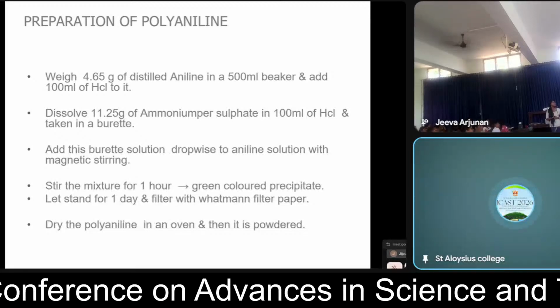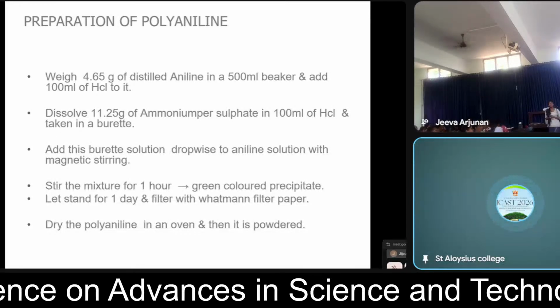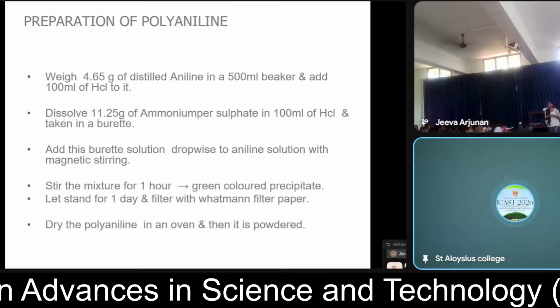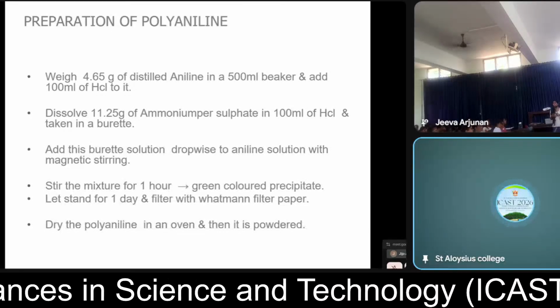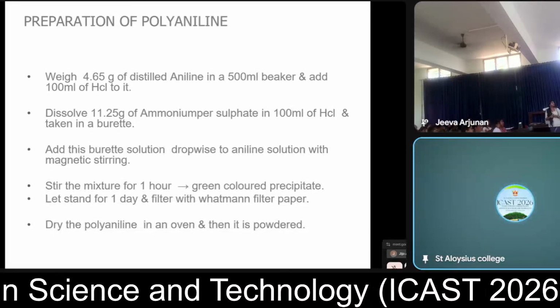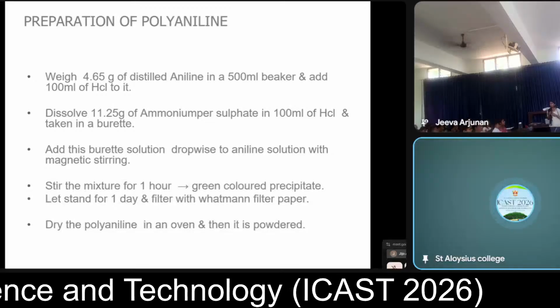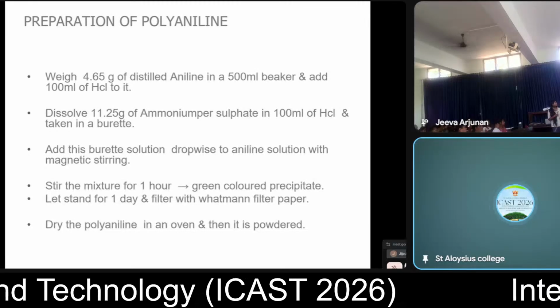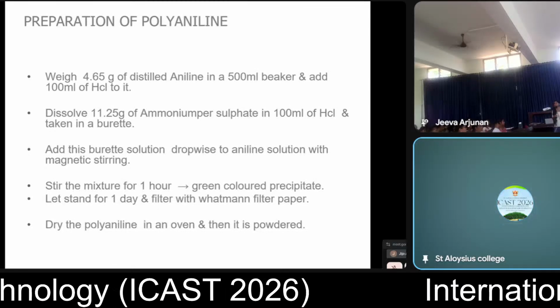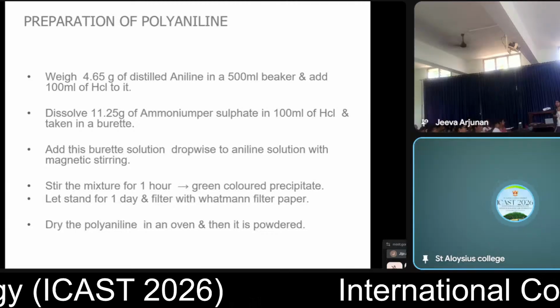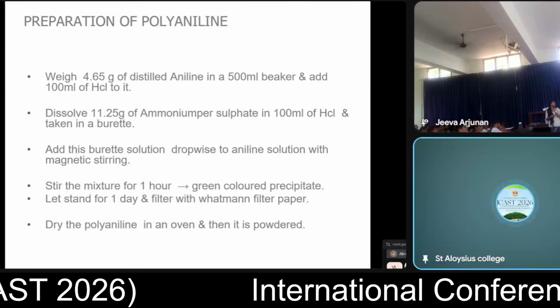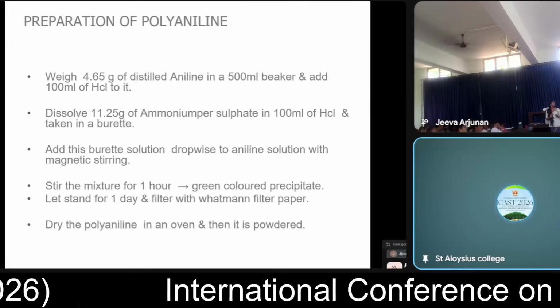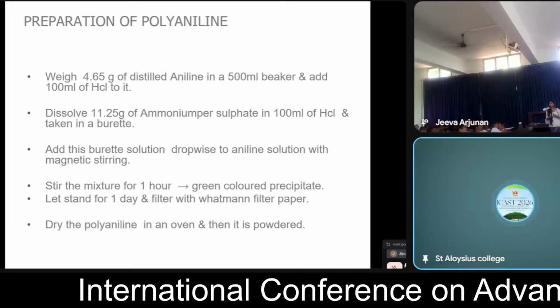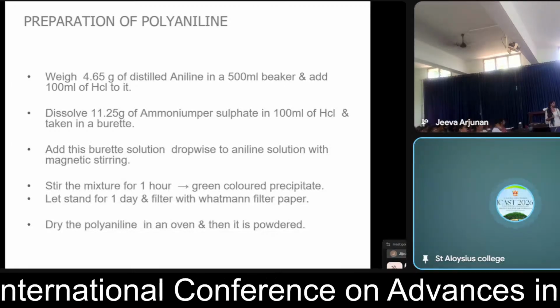For doping of polyaniline, doping can be done by using acids like hydrochloric acid and H2SO4. Here we use HCl. What really happens when we dope polyaniline is that the imine nitrogen of the polyaniline gets protonated by the acid, and we can dedope it using a base like NH4OH.